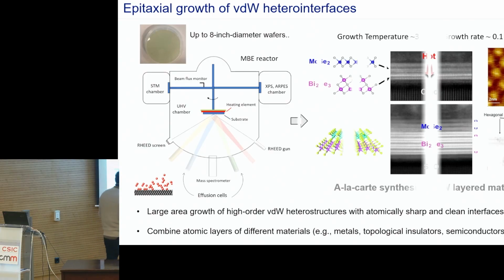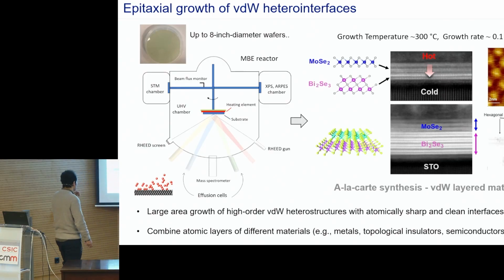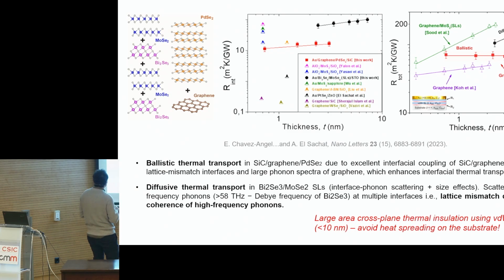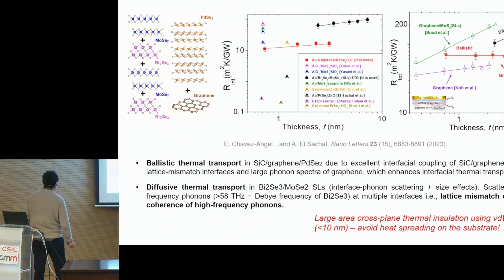So we can really know what kind of material we grow, what kind of heterostructure, and all their properties. These are some examples of what we grow: bismuth selenide, molybdenum diselenide, and you see a bilayer of molybdenum diselenide and bismuth selenide of 1 nanometer grown directly on STO substrate. And we made these superlattices, made of bismuth selenide and molybdenum diselenide, so we create several interfaces on top of each other, and then we grow graphene and several layers of palladium diselenide.